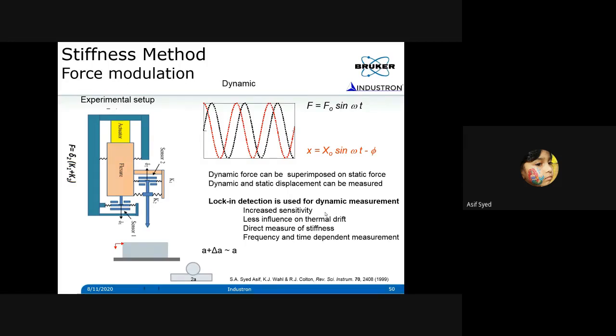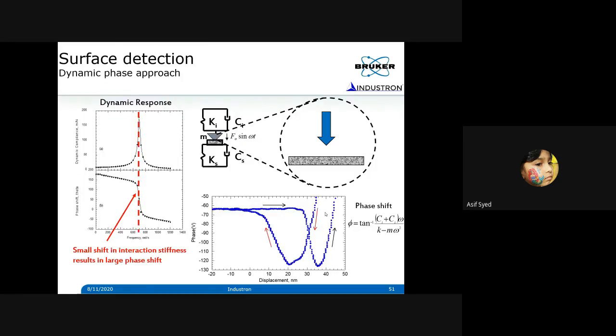This is something that I developed during my postdoc work at Naval Research Lab that was later commercialized at Industron. Using this approach, you can modulate the tip, which means that you are applying a sinusoidal force to the tip, bringing the tip close to the surface and trying to measure whether there is any phase shift between the tip and the sample. If you see a phase shift, it's mainly due to some kind of attractive forces. For example, when you run this tip closer to the resonant frequency and bring the tip closer to the surface, any interaction will shift this phase to either the right or the left side, depending upon whether you have an attractive interaction or a repulsive interaction.